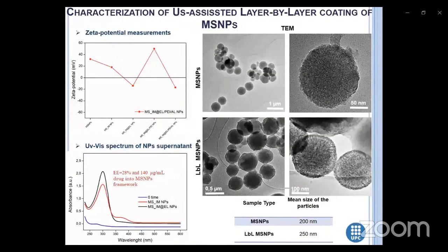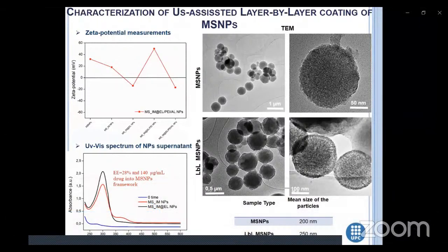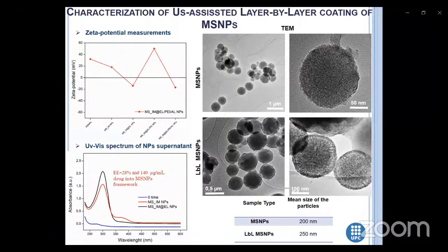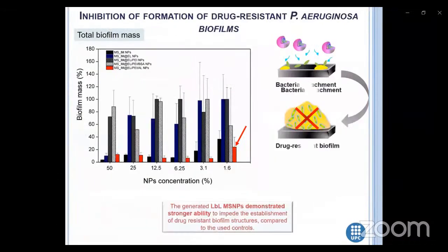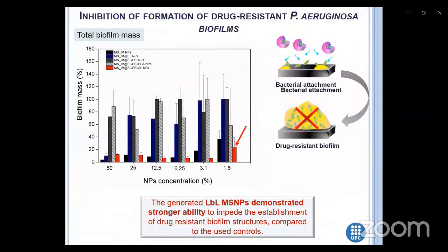So, as we say, the mesoporous silica nanoparticles were loaded with imipenem and subsequently coated with elastin, polyethylenimine, and alginate lyase in a layer-by-layer strategy. The encapsulation efficiency was determined with 28%, and the drug concentration was 140 micrograms per milliliter. The variation of the zeta potential values confirm the successful layers deposition. The TEM images indicated spherical shapes of the nanoparticles with mean size of 250 nanometers.